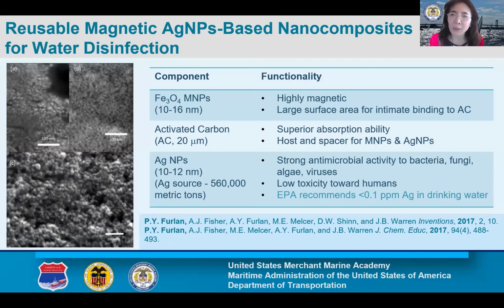Silver nanoparticles demonstrate potent antimicrobial effects against bacteria, fungi, algae, and viruses at very low concentrations with minimal sensitivity to contaminants. We believe silver nanoparticle-based nanocomposites are the most practical and promising antimicrobial agents for water disinfection. However, the EPA recommends less than a 0.1 ppm level of silver in drinking water, and many reported silver nanoparticle-based antimicrobial agents release silver at levels 5 to 100 times higher.